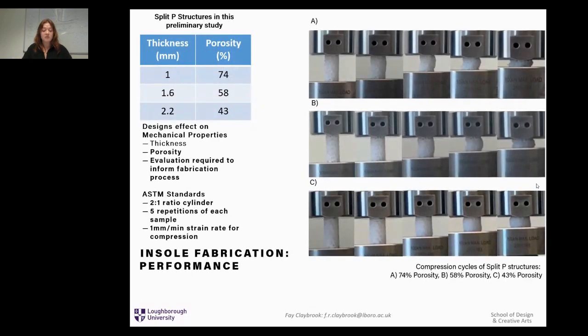So given that there is limited investigation of elastomeric formed TPMS structures, in this preliminary study, the split P TPMS structure was chosen, and the resulting compressive properties with varying porosity using the TPU and the FDM additive manufacturing fabrication, we can create an image of the capabilities of what this can do. So the TPMS structures are a new approach for the replacement of this medical grade foam, and there is only one other study by Holmes et al. 2022 that tested the gyroid structure, and they reported that if they change the internal porosity of these structures, the mechanical loading conditions can be tailored to match the compressive properties of foams that are currently on the market used for diabetic foot insoles.